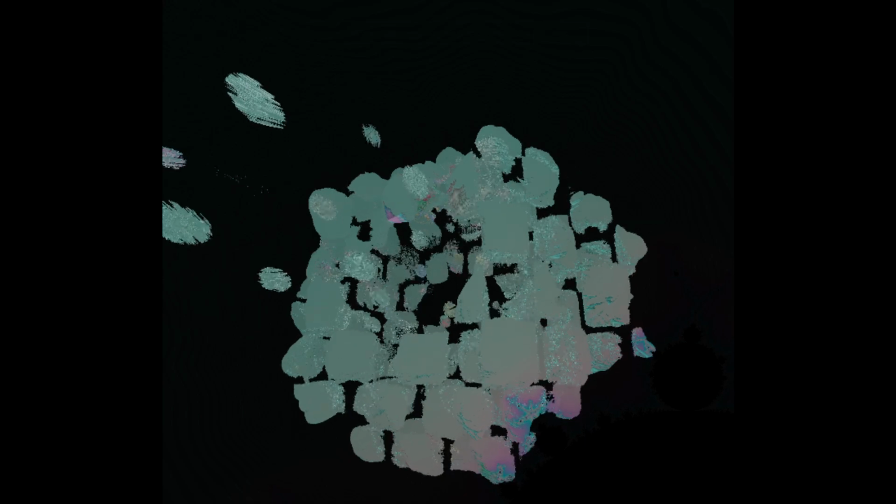In magic angle TBG, the flat bands localize the electrons somewhat within the Moiré superlattice sites. If you try to put two electrons on the same site, or nearby, the energy cost due to Coulomb repulsion becomes enormous, much larger than the tiny kinetic energy they have available to hop away. So the electrons effectively get stuck, they forbid each other from moving onto already occupied sites, and the whole system locks up into an insulating state. This is often described using the Hubbard model, where this competition between hopping t and on-site repulsion U is key. Mott insulation happens when U is much larger than t. They observe these insulating states at specific integer fillings of the Moiré bands, for example, when each artificial atom in the Moiré lattice has exactly 2 electrons, or holes.